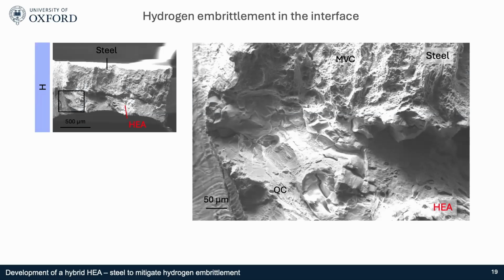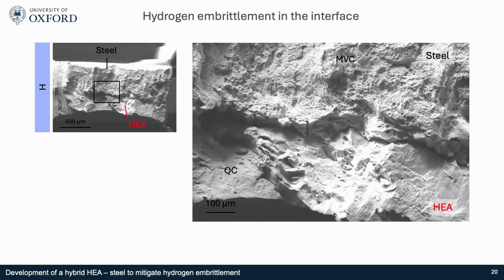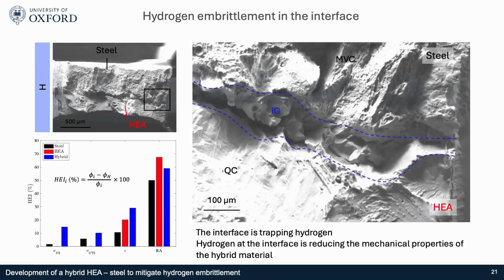So we went into more detail in this interface area, and we saw that in the steel zone some microvoids were observed. Then in the high entropy alloy, the quasi-cleavage zones were observed as in the previous high entropy alloy samples. But in the interface area, we saw some intergranular cracking. The same was observed in the middle of the sample, here, and also on the other side of the sample. So these results suggest that the interface is trapping hydrogen, and the hydrogen at the interface is reducing the mechanical properties of the hybrid material, as we can see here in the hydrogen embrittlement indexes.